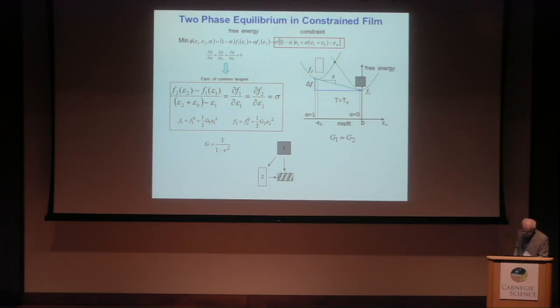In this case, the solution of the problem goes through a Legendre transformation, and then you can find something which is called the method of the common tangent. So we understand there is a common tangent between the two, black and gray phases. So we have some mixture. The diagram looks now like this.